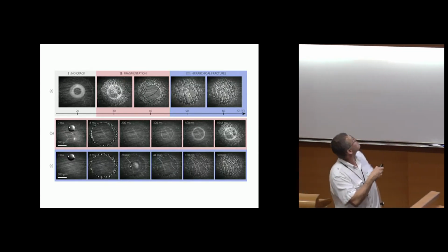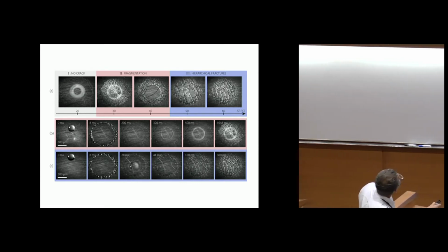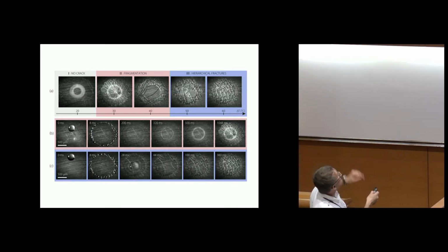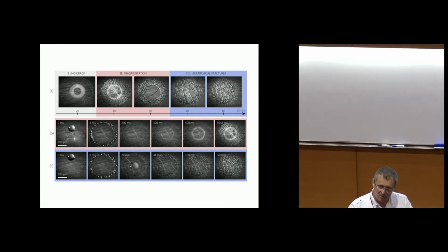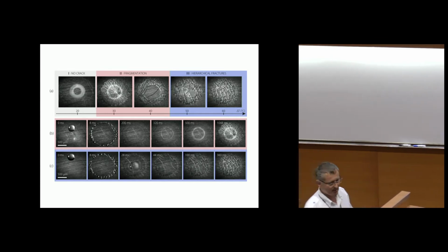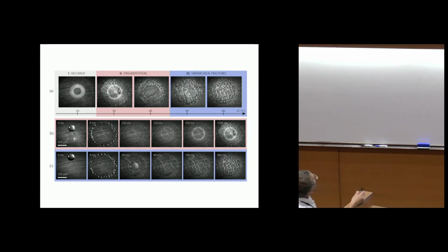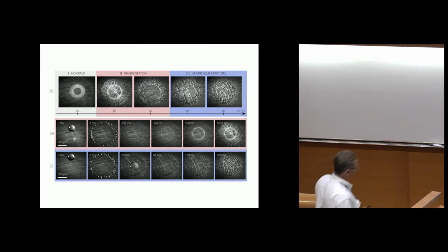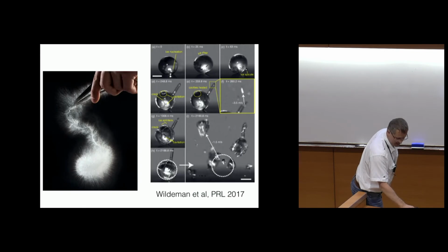Just see that, as for this case of impact, as the temperature is varying, as you go to cooler and cooler substrate temperature, at first nothing happens, no cracks, so you can keep that as long as you want. Then fragmentation: the drop is totally frozen, and then you wait, and suddenly it breaks. Or you can have cracks appearing during the solidification process. And you see that these patterns are very different from this one. So we have a phase diagram, but I think I will go on.